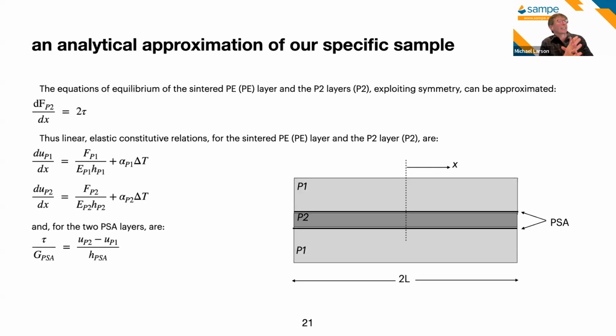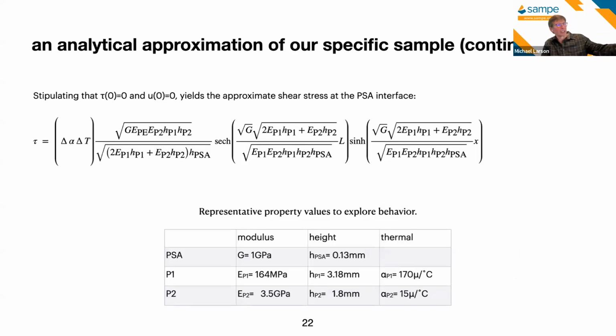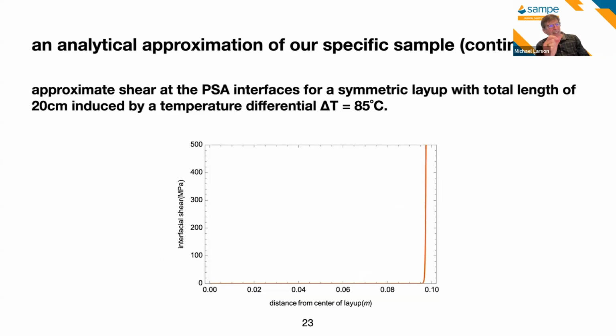We can assume that we're going to drive a delamination by having a temperature change, where P1 and P2 have two different coefficients of thermal expansion that is going to drive this, opposed by some shear on the interface. So some simple representations turn into this governing equation for the distribution of shear to satisfy equilibrium. And then using some typical materials that might be a stiff plastic with a much more compliant middle layer with PSAs in between, taking some typical material properties for the thermal expansion, the modulus, thicknesses of these things, what we see, not unexpectedly, is a distribution of the interfacial shear that's symmetrical with the center